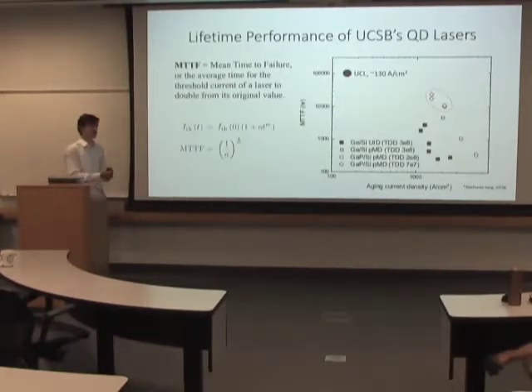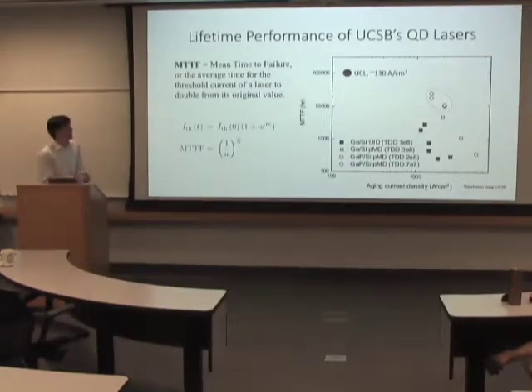The thresholds actually deteriorate as you go — a threshold of 3 milliamps after continued usage could eventually turn into a threshold of 5, 6, 10, or 20. And so if you're putting this in a computer, that basically determines the lifetime of the component.